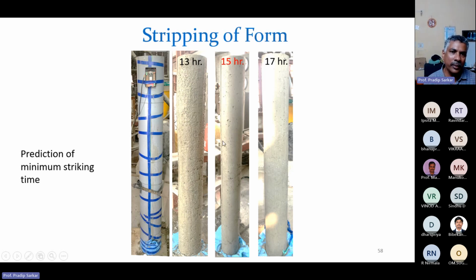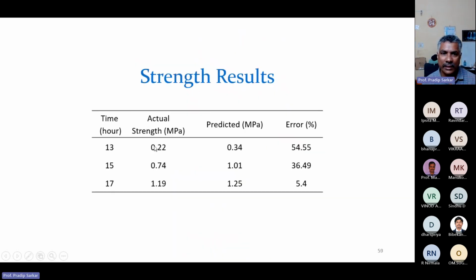But at 15 hours when you remove, the same concrete is cast in 4 different... You mean to say that as the time is increasing, the finish of the setting is also getting good? Yeah, right. When time is increasing, setting is better. And then at that time when I remove, I am checking what strength is achieved. So this is the actual strength available from the break test, and this is the strength that we are getting from the LoRa 1 device that I mentioned.